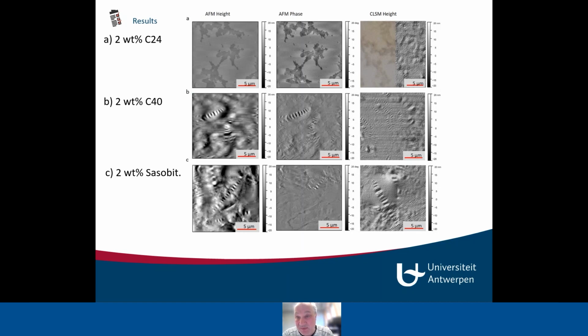I split the image of the confocal. On the left is the optical image. On the right, you have the laser scan image. So you see in the optical image the decolorization, and then on the other side, you see the laser scan. If we increase the length of the waxes, so the chain length, and we go to a C40, then at that moment we can see that we start to generate these bees, and we can see this in the AFM and in the confocal images. Also, if we take a commercial wax, like Sasobit, and we add 2%, then you can see clearly again the creation of these bees.